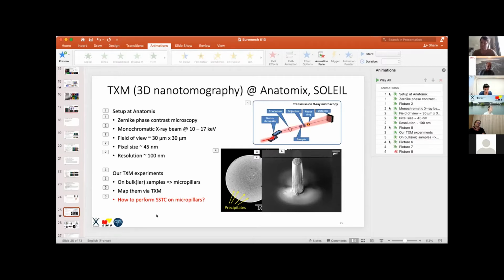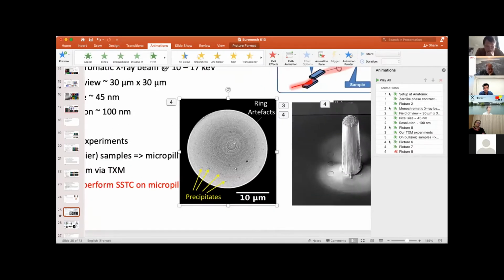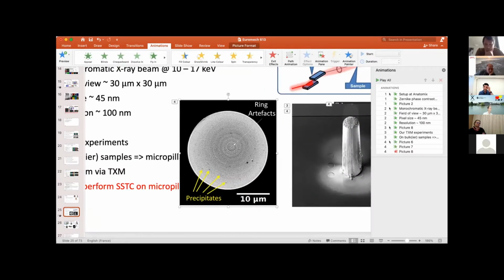Yeah, so that's a very good question, because we were wondering the same. There are a bunch of precipitates that are smaller than 100 nanometers in size, and quite a few that are more. And we actually see quite a large density of precipitates. So you can already see these precipitates in this slice, and this is at 100 nanometer resolution already. So in DED, you would see these kind of precipitates having an average size greater than 100 nanometers, so you would at least have them in 1 pixel. And here we are having them in more than 1 pixel.